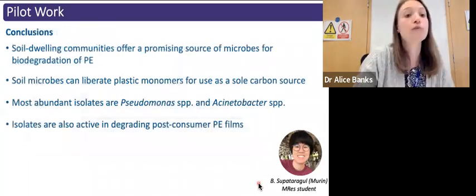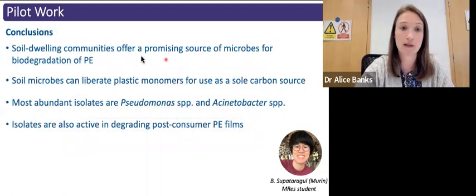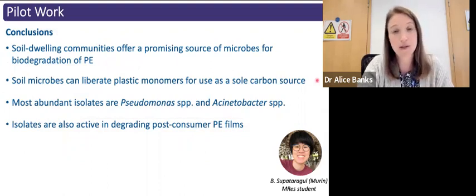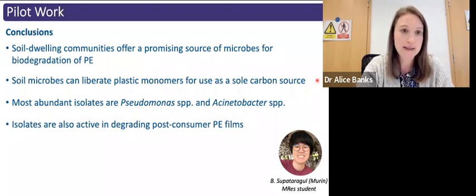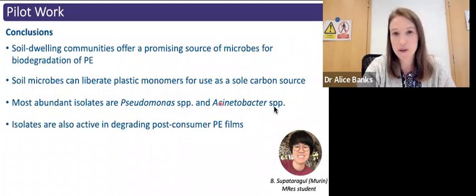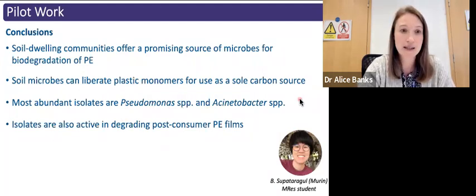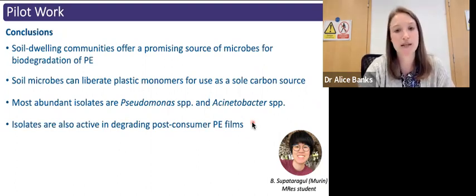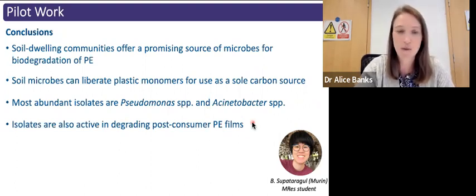So to conclude Murin's work, she found that soil-dwelling communities offer a really promising source of microbes to degrade polyethylene, and that soil microbes are able to liberate the plastic monomers and use these as a sole carbon source for growth. And one of the most abundant genera are Pseudomonas, and also Acinetobacter to an extent. And these isolates also seem to be active in degrading post-consumer PE films, particularly in the presence of a rich medium. And the data that Murin collected during her master's project has led on to this IMSE proposal, which we've recently started. So I'm going to next talk to you about what we're hoping to achieve here.